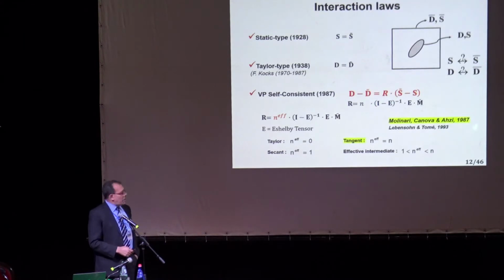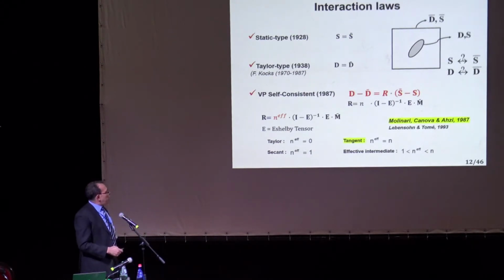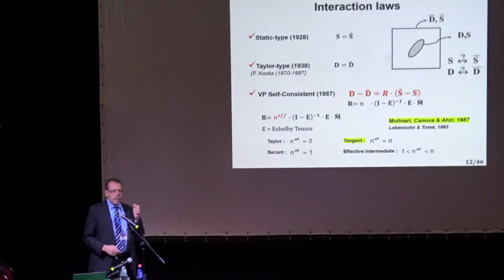This R, in the work I have done with Anna Molinari and Gilles Canova, we found that this R here is N, which is the power coefficient, the inverse of the rate sensitivity of the material. It's related to the Eshelby tensor through this, and M bar is the macroscopic compliance tensor, okay? We used the tangent formulation for the single crystal behavior to reach this relationship. A few years later, Lebensohn and Carlos Tomé from Los Alamos modified this by multiplying by N effective. In fact, what they noticed is if we use the secant modulus, then we will have not N, we will have 1 here, okay? But I'll tell you why in '87 we did not use the secant modulus, we used the tangent.